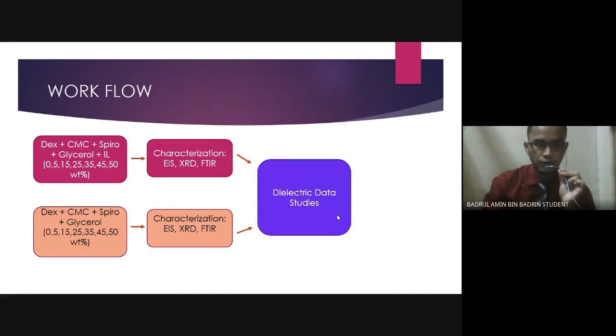So both systems are characterized with EIS, electrical impedance spectroscopy, to study the electrical behavior of the samples, XRD, X-ray diffraction, to study the angles that scattered from the samples, and FTIR, Fourier transform infrared spectroscopy, of the samples.